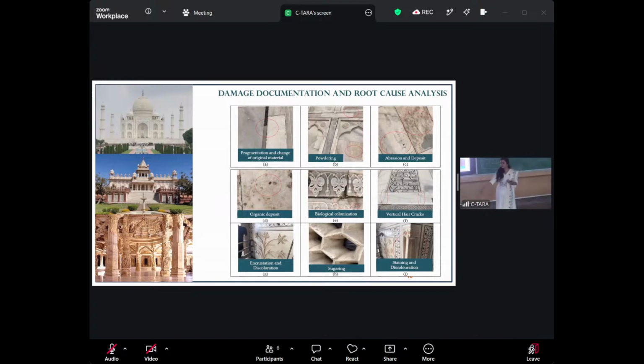You see manifestations in different ways. What you need to do is find the root cause of this. Among all of these, the most prominent, I wouldn't say damage, but the most prominent degradation mechanism that you would observe if you go to any of these structures, let us say, take the Taj Mahal as an example, would be staining. Staining is very commonly seen, and in fact in the Taj Mahal, they do destaining methods periodically, every 2 to 3 years. What they do is something called poulticing, which is very similar to the facial pack we use. You take a paste and apply it over the marble. Upon drying, with capillary suction, it will suck up the stains and all the dirt or dust from the marble, and that will be on the paste. On drying, you remove the mask, or the poultice. It's called a poultice. And now the material is cleaned.